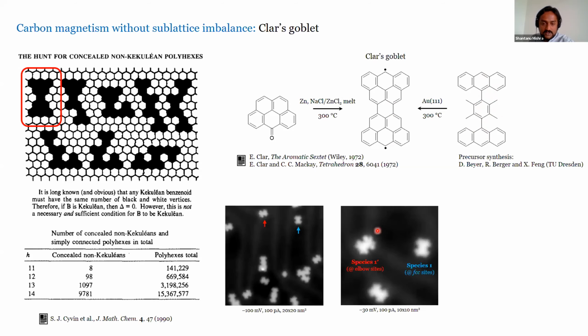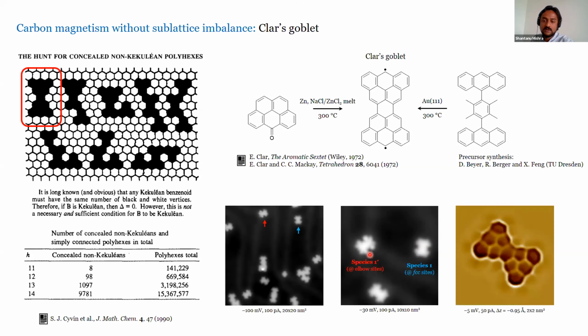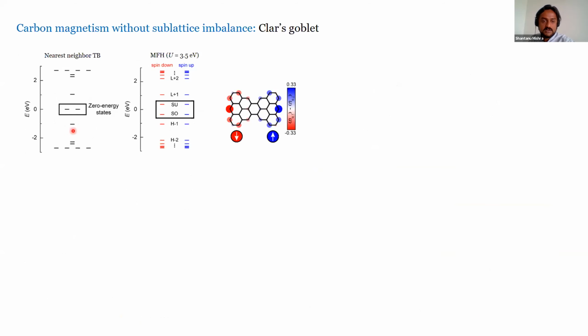So this is how things look on the surface. You have individual molecules and you have some covalently fused clusters. Now these molecules come in 2 different flavors. One, which I'm going to call species 1, resides exclusively on the FCC lattice sites of the gold surface, and it looks completely symmetric, while the other, which I'm going to call 1', is exclusively found at the herringbone elbows. Now, species 1, let's talk about that first, is indeed what we set out to prove, that it's Clar's goblet. And now let's look at the electronic structure once again from a theory point of view.